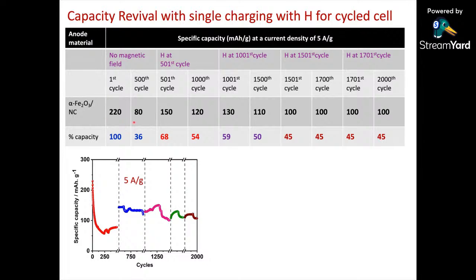You can see that without any magnetic field, from the first cycle to 500 cycles, the capacity has decreased to 80 from 220 milliampere hour per gram, at a current density of 5 ampere per gram. So the percentage of capacity has decreased from 100 to 36. The magnetic field is applied at 500 cycles, and it has increased from 80 to 150. Again, we applied the magnetic field, and you can see that very close to 2000 cycles, the value is almost two thirds of the value obtained at the 500th cycle.